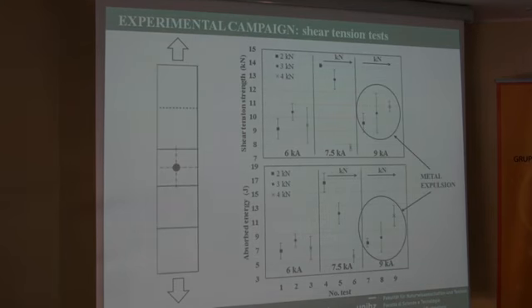Here you can see instead some graphs showing the results obtained from the shear tension test. In particular, here you can see the mechanical strength obtained by the test as peak loads. Due to the nature of the welding process, we have to consider that we have quite a large scattering, but we can identify a sort of trend in these results.